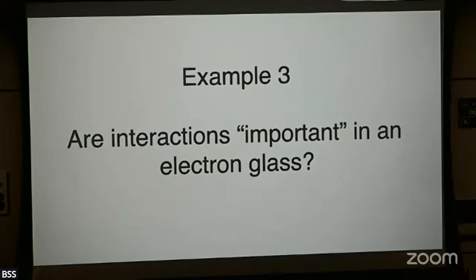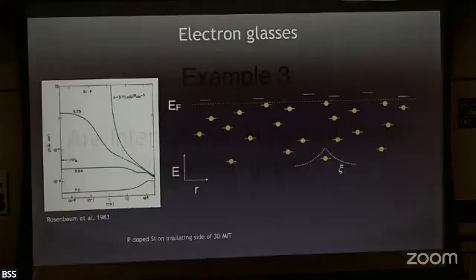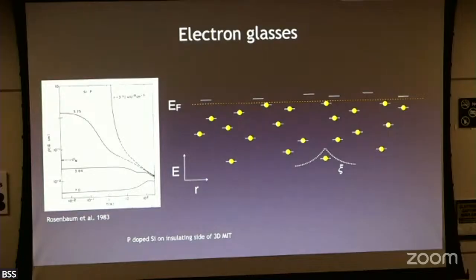Yeah. So phosphorus-doped silicon is, we would imagine, a crystalline ensemble of silicon atoms, where something like 1 in every 10^6 silicon atoms is replaced by phosphorus. Okay? So phosphorus has 5 valence electrons. 4 of those electrons go into making bonds with their neighbors, but 1 electron is left over, and that electron goes, at low densities, when every phosphorus is really far from each other, into some kind of quasi-hydrogenic orbital where it's orbiting around. The Bohr model, the Schrödinger equation, would be some kind of rough guide to what the physics of that is.